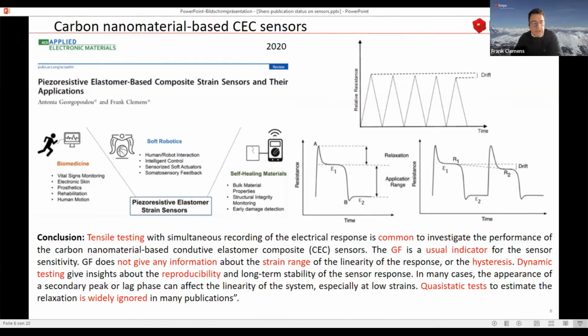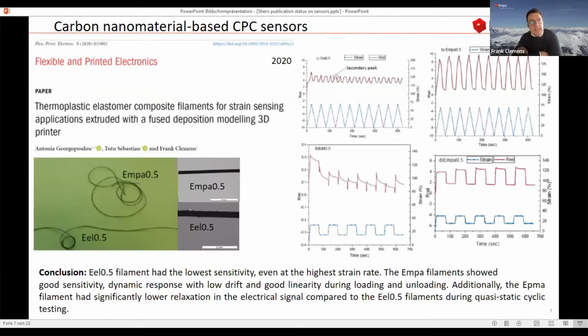So according to this literature research, we started to develop our own sensors. And you can see here two kinds of sensors. This is a sensor which we developed ourselves. This is a sensor, or the material for it, which you can buy on the market. And here what we did is, by fused deposition modeling, by 3D printing, we extruded and printed both of these materials, and you can really nicely see in the graphic what the problem is. If you have this commercial sensor material, then it is almost impossible to measure anything at low strain. You see, if we go up to 70% strain, we have a secondary phase, a peak. And this secondary peak tells you that your sensor is not accurate enough to measure at small strain levels.